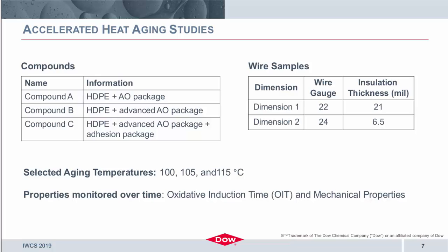So now we'll talk a little bit about the studies that we did. In particular, we looked at 3 different compounds commercially available on the market, where the real difference is in the additive package. So again, looking at the thermal stabilization, compound A was a high-density polyethylene with a standard additive package. Compound B had an advanced additive package, and compound C an advanced additive package plus an adhesion promoter package for better bonding to the conductor. In this case, we did use wire samples. So we extruded 2 different cables, one on a typical 24 gauge wire with a thinner 6.5 mil insulation thickness, and also a 22 gauge wire, more typical of your higher category cables, with a higher insulation thickness of about 21 mils.